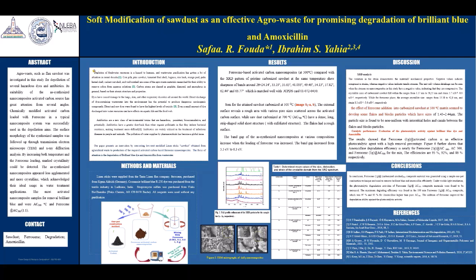Synthesis. Sawdust was cleaned regularly with water to remove any dust from pollutant had accumulated and dried at 120 centigrade. Sawdust is carbonized at 3 different temperatures, 300, 500, and 700. In addition, the carbonized sawdust at 500 centigrade was modified with different ratios of ferrocene.